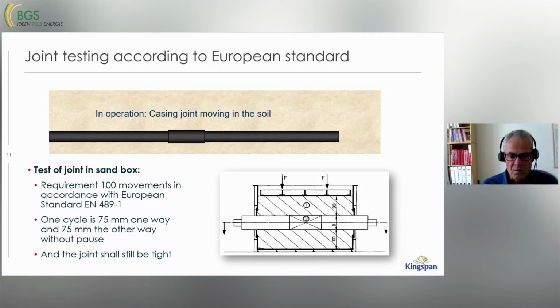And then we start to move this piece of pipe 75 millimeter to the one side, back again to the middle, 75 millimeter to the other side, and back to the middle. And that shall happen 100 times, so it shall be repeated 100 times.